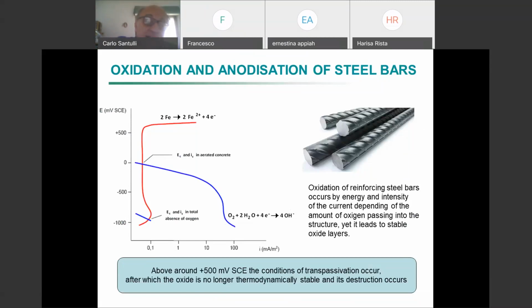Here we have transpassivation, and basically the oxide is not thermodynamically stable, and therefore is going to be destroyed quite abruptly. In most cases, we have an oxide which is stable, so we are in a situation where iron is the anode, but the oxide is going to stay there. And basically, we have oxidation, but not corrosion in most cases.